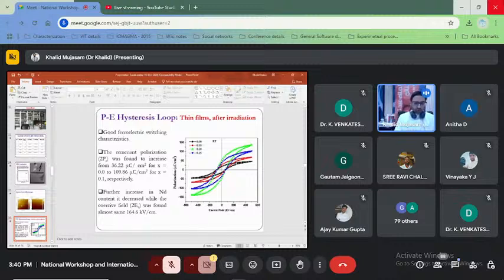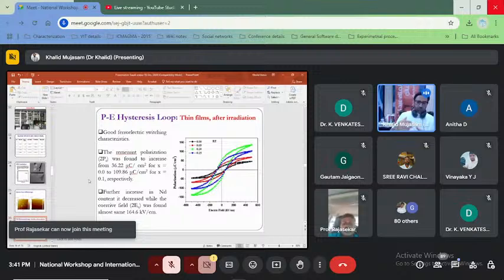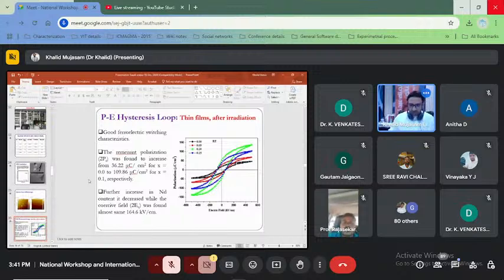That yes, with the usage of the IUC beamline facilities, we can have tuning of the properties. And what we achieved was 36.22 microcoulomb per centimeter square for the 0 concentration, and 109.86 microcoulomb per centimeter square for 0.1 doping. That was something very fascinating, and we were looking at whether we can use this type of technology, this type of synthesis mechanism, to do further enhancement in our properties.